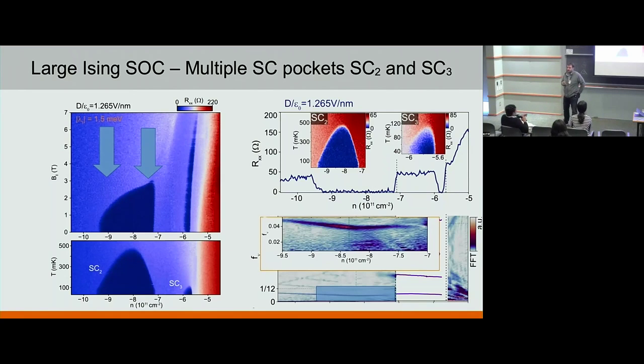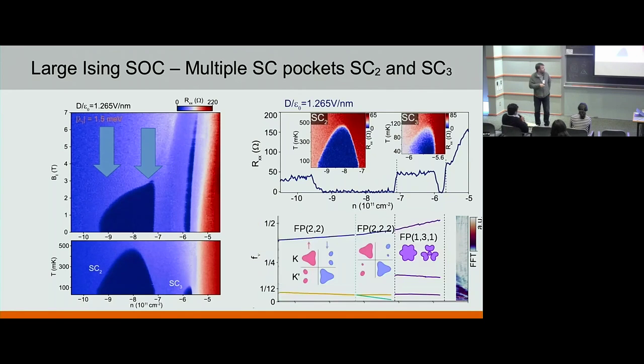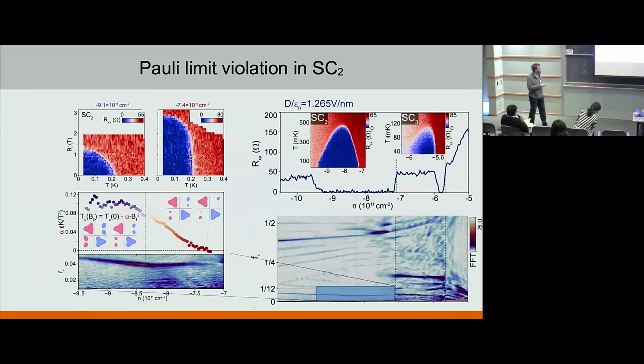I just want to confirm a couple of things you said. So the puzzle you mentioned is that if I look at the trend for alpha, the coefficient of B squared, you would think that the superconductor on the right half of SC2 would have a larger field. It responds less to the magnetic field, so you'd think it would have a larger critical field. But in fact, it has a smaller critical field. Was that the puzzle you were mentioning?